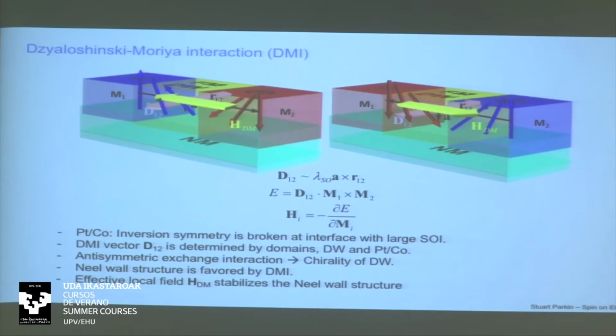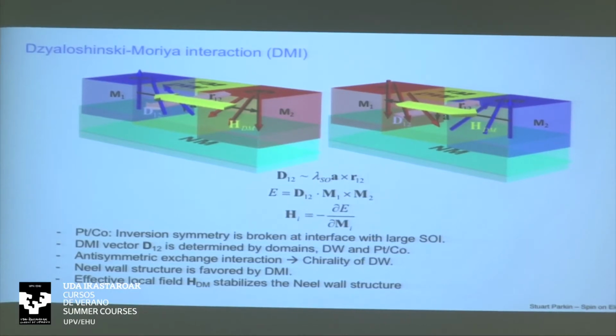But it means that along this racetrack, each domain wall has the same chirality. So if you like, as you go along this racetrack, the magnetization will be going from an up to a down direction in a chiral helical fashion. Later on, I want to show you how in bulk materials, the same interaction can lead to helical phases, and it can also lead to skyrmionic and anti-skyrmionic phases.